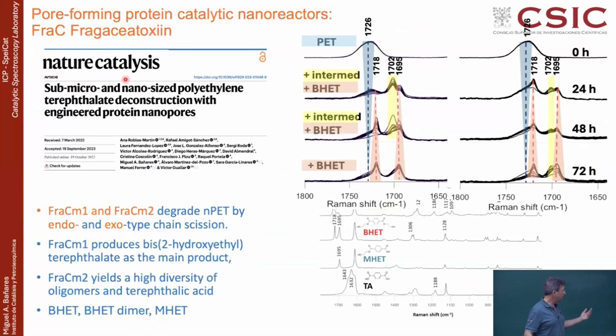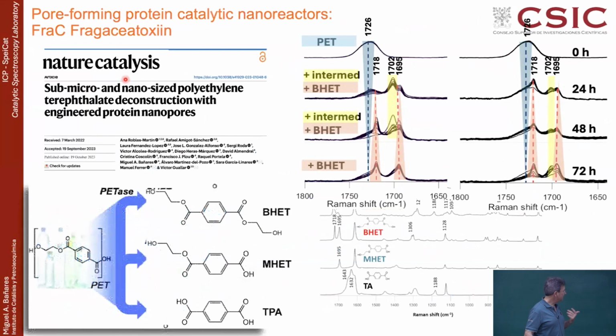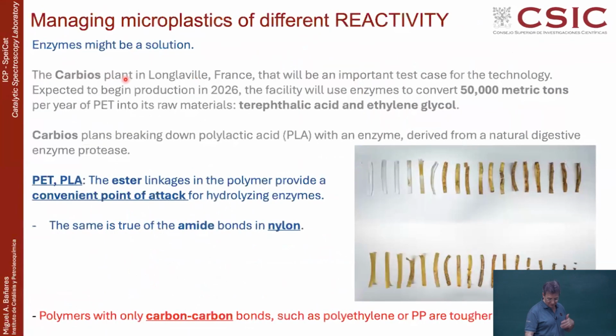Of course, now a lot faster than what is happening in the digestive system, because this is already a very dedicated and very focused analysis. And you can get a lot of products out of the polyethylene terephthalate, and then you start to get the monomers and dimers, and then you can use that for further fabrication. So that is telling you that nature is already able of coping with plastics. Our system is already coping with plastics to some extent. You can engineer enzymes to cope and to degrade the plastics.